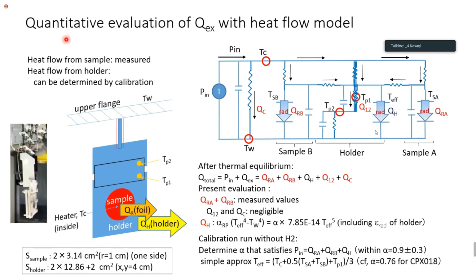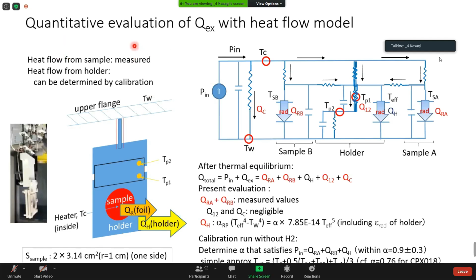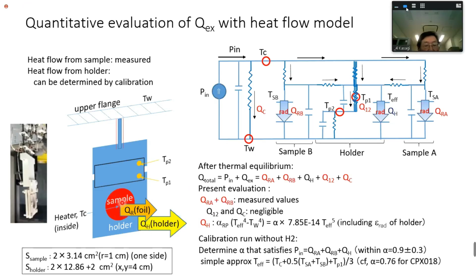We need a model to extract a quantitative evaluation. Evaluation will be quantitative, because not only the radiation from the sample, we have radiation from the holders. So therefore, we just put a simple model again to the sample surface and the holder surface over here, and then various equations over here. But what I want to stress is the radiation from sample B and the radiation from sample A. These are measured, and we need an effective temperature over here. To do that, we use the temperature core and the temperature measured over here. These are the measured values.